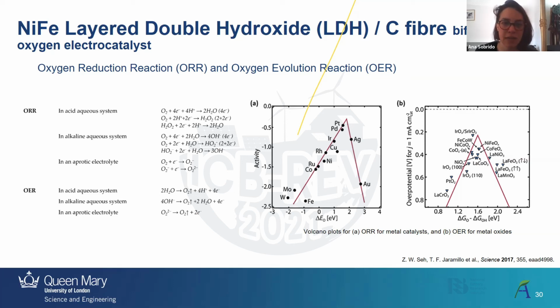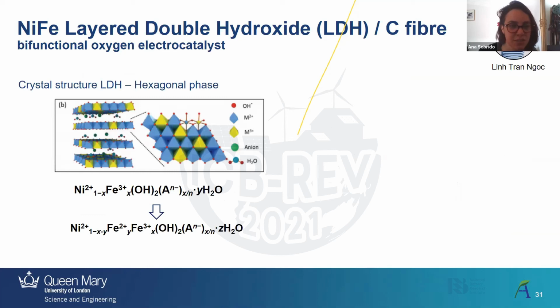Here we have volcano plots for the oxygen reduction metal catalysts and the metal oxides in the case of oxygen evolution, and we can see the best are around platinum and palladium. Iridium is not that good for reduction, but it is better for oxygen evolution. These are not very sustainable materials, and they're really scarce and difficult to get. So the idea is, can we develop alternative materials that still perform at acceptable levels? That's our premise, our goal.